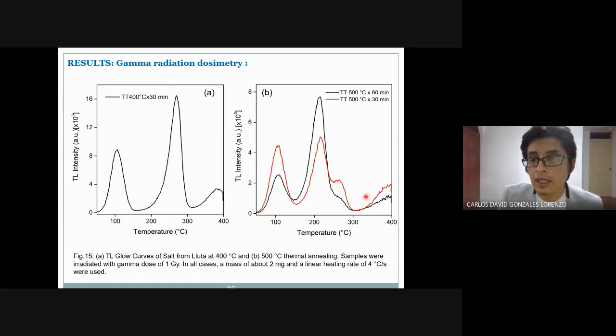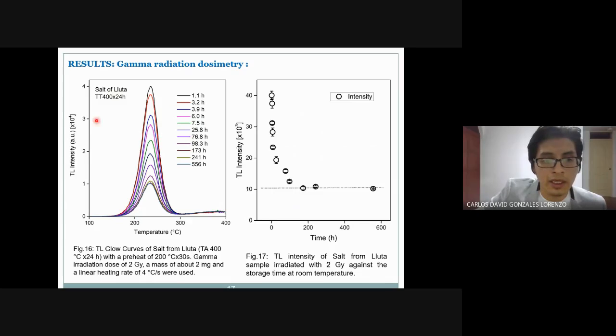So after a given time, we could arrive at stability of this TL intensity. For these reasons, the sample of salt of Lluta was given a previous thermal treatment of 400 degrees, but for 24 hours, with the objective of reaching stability in the TL intensity obtained.